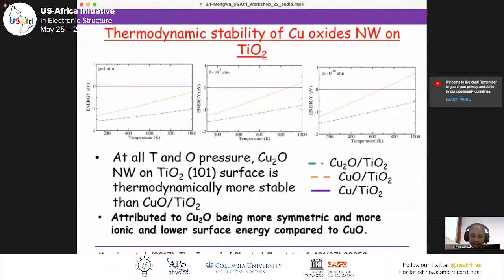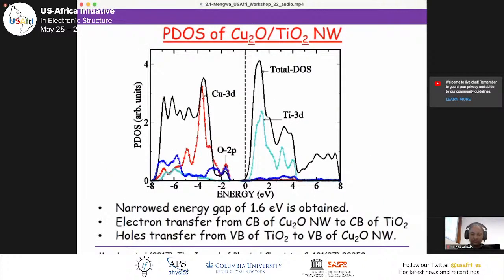The thermodynamic stability of the copper oxide nanowires on TiO2 was also studied, and it was found that at all temperatures and pressures, the Cu2O nanowire on the TiO2 101 surface is thermodynamically more stable than the cupric oxide. This is attributed to Cu2O being more symmetric and more ionic, and also having lower surface energy than CuO.